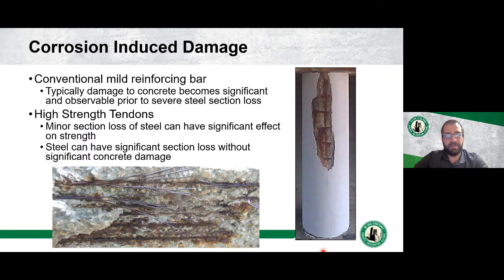For conventional reinforcing steel, typically we see things like this column here where we get a spall and some rebar corrosion, and that's an indication to most engineers that we need to start addressing this structure, right? We've got some damage that's observed. Typically, we're going to see these kinds of spalls occur before anything structural is a matter with this element. Obviously, we have some section loss and some deterioration, but from a structural point of view, we're probably not very worried about this column.